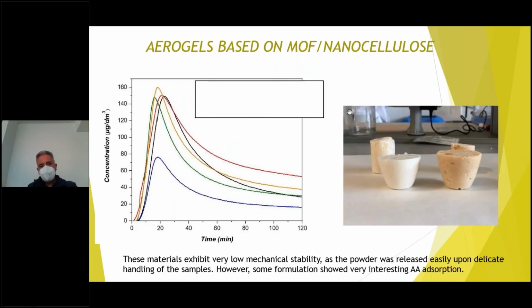Well, in the framework of the NEMOSINE project we made this kind of aerogels, as you can see in the photography on the right side, several materials prepared with the combination of MOF on nanocellulose. Basically, for the preparation of these aerogels, we use lyophilization, the freeze drying process. In this case we do not really have aerogels, we have cryogels, as I have explained. And as you can see in the performance of these foam adsorbent materials, we can see very impressive results.